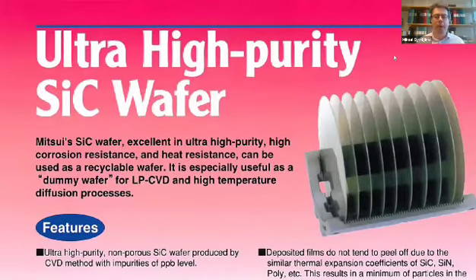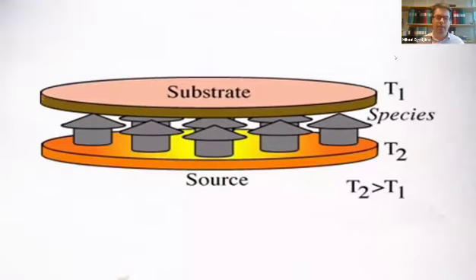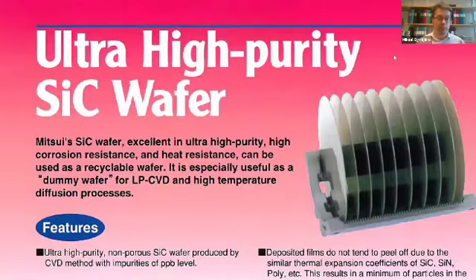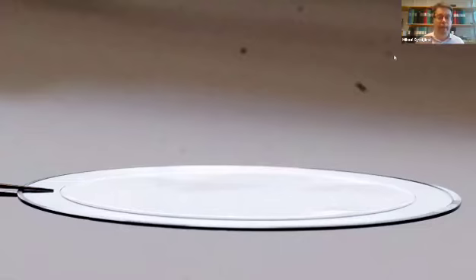And instead of silicon carbide powder, we were using ceramic silicon carbide as source material. So in this bottom image, the source, it is ceramic silicon carbide, which is actually possible to buy because this is used in silicon growth as dummy wafers. So for example, Mitsui has such material in wafer size. They are grown by CVD on graphite, and then you get polycrystalline silicon carbide, a ceramic, and that is used for other purposes. But we were using it for our growth. And I will come back to this ceramic silicon carbide when it comes to one of the latest opportunities which we have got. So we are using such ceramic, and the aim is to grow very thick layers.